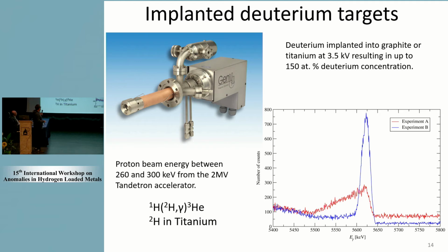And what was not mentioned yesterday, we know that this ion gun, it's a microwave plasma ion gun, produces mostly H3 plus ions. Then there is some H2 plus and also some protons as well, or deuterium, whatever you put. So this is what we use to implant, and the outcome of the implantation can be seen here. This is the gamma ray energy of this reaction, protons plus deuterons. We get the gamma ray, and the shape of the gamma ray already tells you the distribution of your deuterium in the target, which is important for further analysis. So in this case, most of the deuterium was on the surface, and this one was in the bulk. So you could see the cross section all the way down to zero energy.